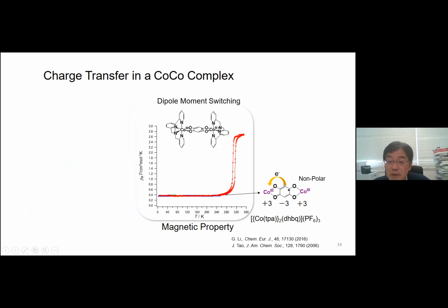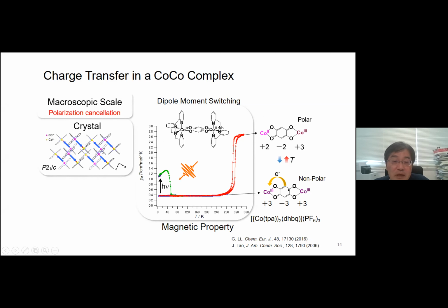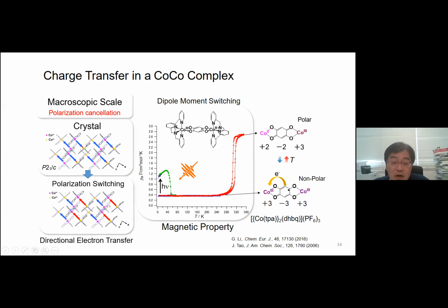This compound exhibits electron transfer between metal and ligand. Cobalt 3 and cobalt 2. So these molecules exhibit dipole moment switching at a molecular level. And furthermore, this dipole moment switching is induced by photoirradiation. However, at a macroscopic level, this polarization cancels out. Therefore, to realize macroscopic scale polarization switching, we should control electron transfer direction. We should realize directional electron transfer.